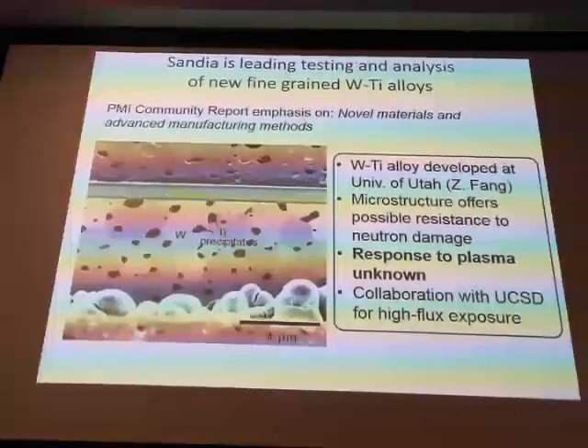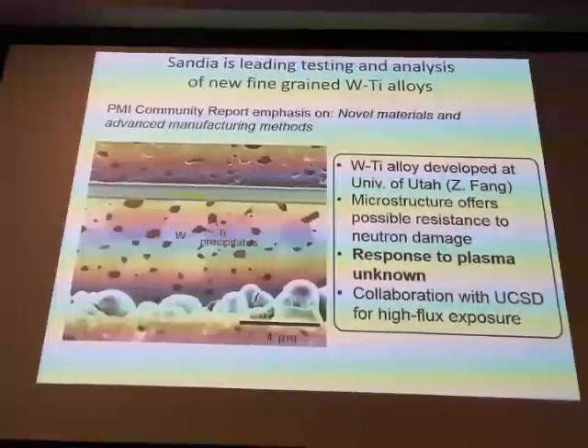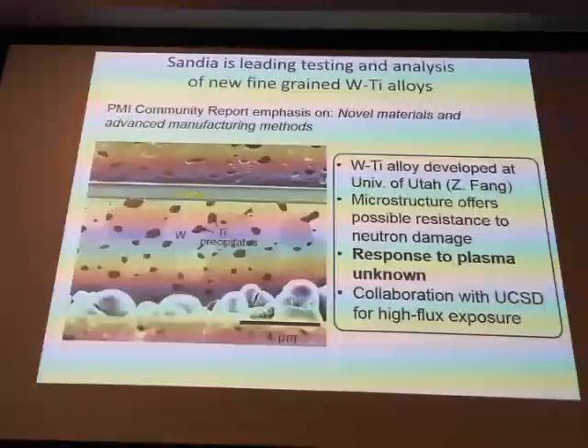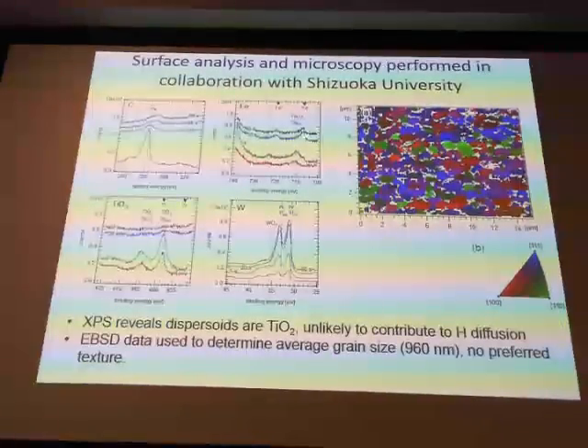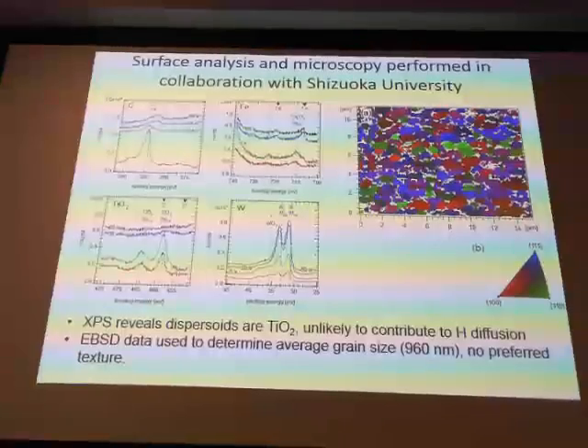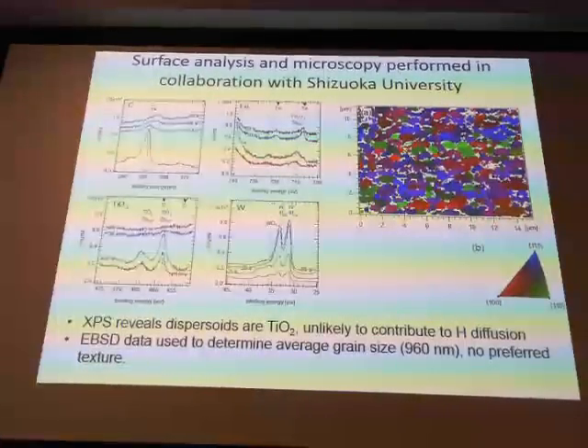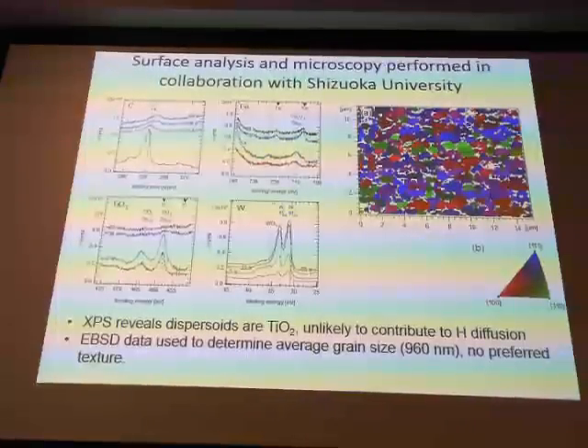Unfortunately, the response to plasma exposure was unknown, so we took some effort to really understand this a little bit better. The one aspect that we were unsure of is, you're introducing these small grains here, but titanium likes to form a hydride when it's exposed to hydrogen. Would the material just disintegrate when it's exposed to a plasma? I guess this image was actually taken post exposure, and you can see it has held up reasonably well. What we found is that the titanium seemed to scavenge the oxygen from the neighboring tungsten, and it formed titanium oxide, which is relatively immune to hydrogen, and as a result, it didn't have such a remarkable effect as what we were expecting.